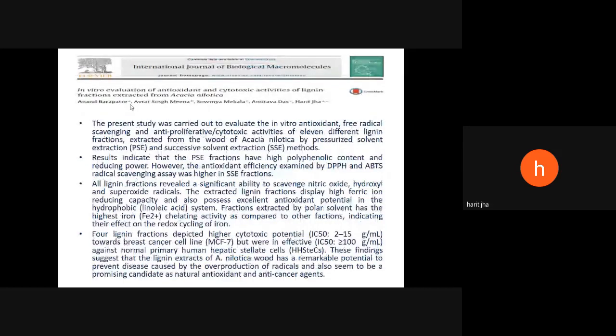In this, we tested the in vitro evaluation of antioxidant and cytotoxic activity of the lignin fraction extracted from the Acacia nilotica. We also tried the pressurized solvent extraction method and successive solvent extraction method for extraction of the lignin. And then we tested their ability to scavenge nitric oxide, hydroxyl, and superoxide radicals. We found that they display high ferric ion reducing capability and have excellent potential in the hydrophobic system. The fractions extracted by polar solvent have the highest iron chelating activity as compared to other fractions, indicating their effect on the redox cycling of the iron.